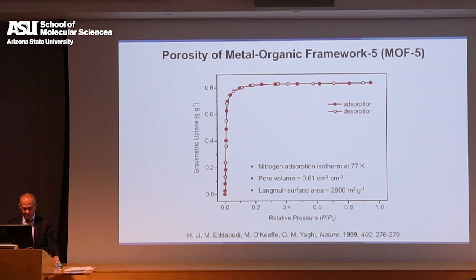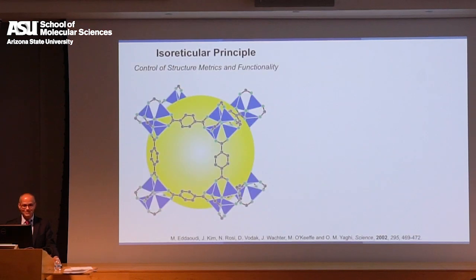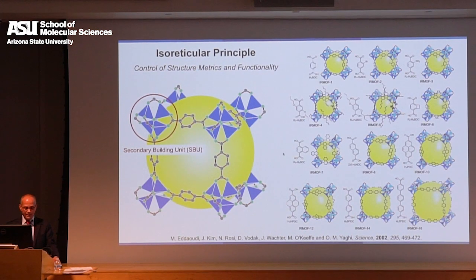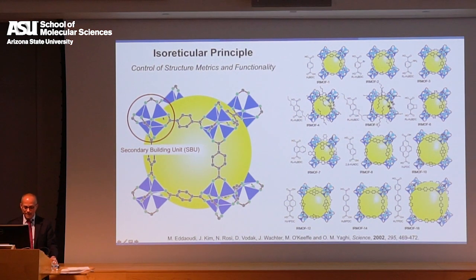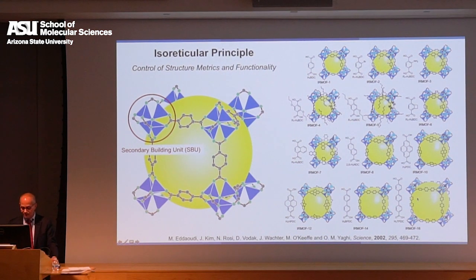But we reported the lowest number that we obtained, just because as an assistant professor, I was worried that I might make a mistake. So anyway, it turns out to be higher than that. And now we have the concept of SBUs articulated by Mike O'Keefe and myself, in that now you take the carboxylate carbons to have a primitive cubic structure. And once you know the conditions under which to make this, you could functionalize the linkers and make the same structure, what we called in those days isoreticular structure, meaning having the same underlying net.